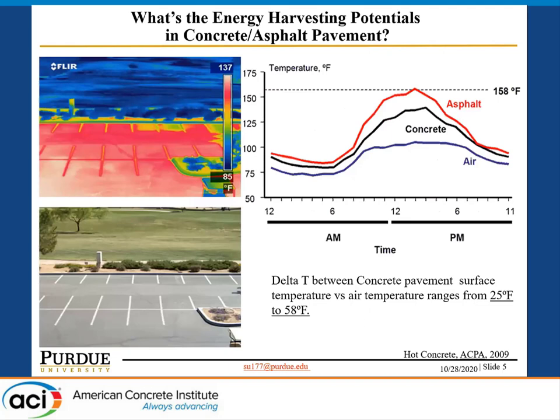So what's the energy harvesting potential in concrete or asphalt pavement or infrastructure? As you can see in the picture on your right-hand side, the time versus the temperature, we have asphalt, concrete in the black line, and air in the purple line. We can observe that the delta T between the concrete pavement surface temperature and the air temperature ranges from 25 degrees Fahrenheit to 58 degrees Fahrenheit. This means it is a great opportunity for us to use thermoelectric material to harvest energy.